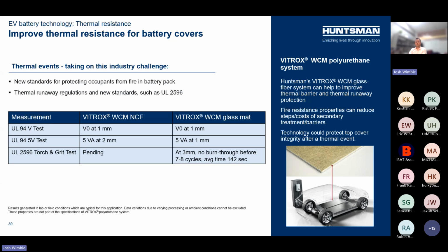So it's really promising as not just a mica alternative, but because this is a self-supporting semi-structural composite, you can potentially enjoy those molding benefits, those quick process times of under 3 minutes that I talked about, while not requiring an additional heat shield or thermal barrier potentially. You're probably aware that aluminum and many thermoplastic composites or sheet molded compounds, except those in the higher range of price, burn through quickly in UL2596 without a mica shield within the battery pack. The Vitrox wet compression molded materials present an option for something that's inherently flame resistant, so you're not only getting the part weight savings of using a composite, but you're potentially also able to get the cost savings of consolidating the two parts into a single lid.